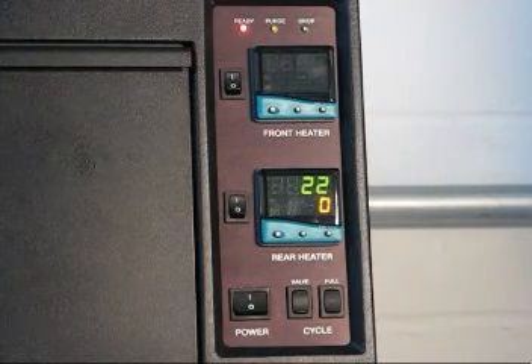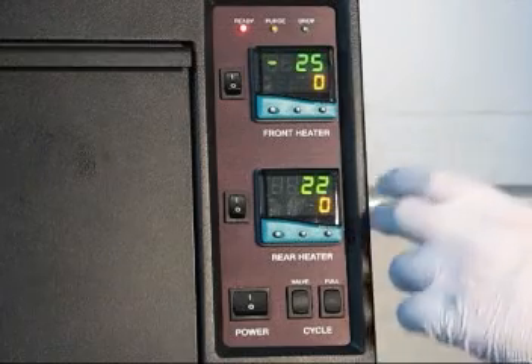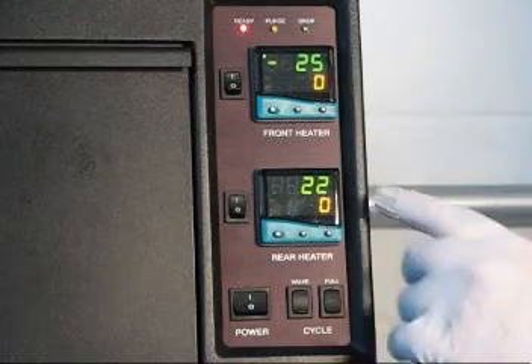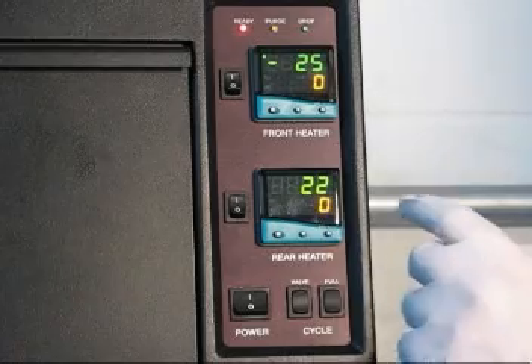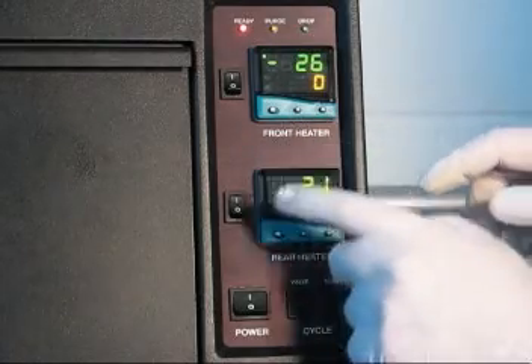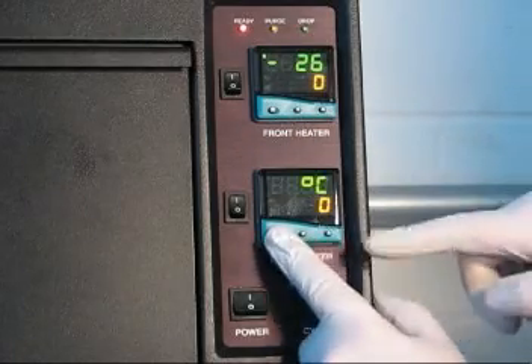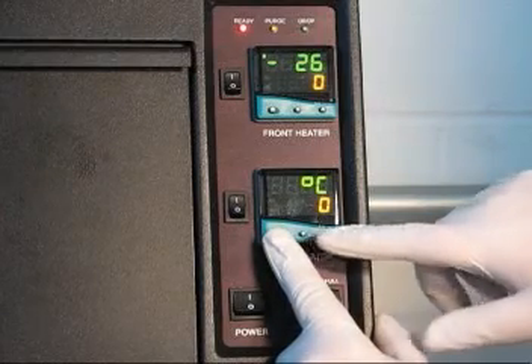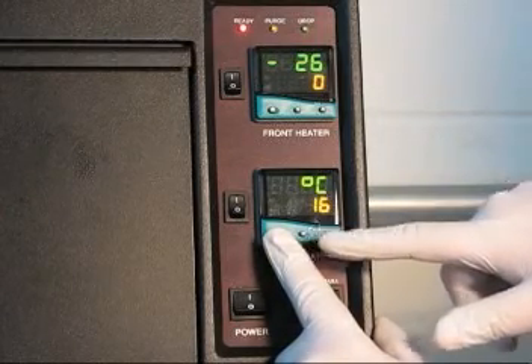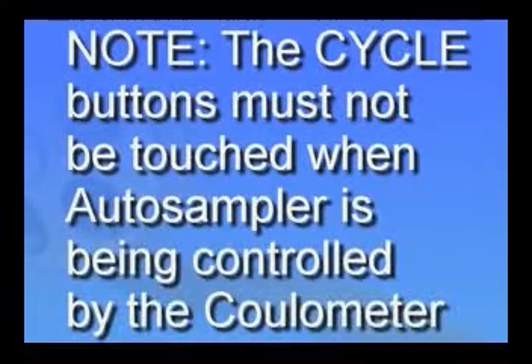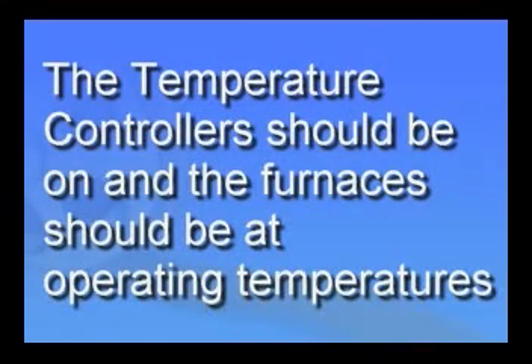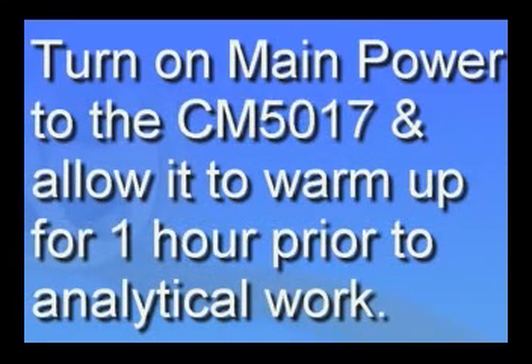Now we will turn on the PID temperature controllers. Each one shows the current temperature with offsets and the set point temperature. To set the temperature, press the star key and hold it down, and use the up and down arrow keys to adjust the temperature. Note that the cycle buttons must not be touched when the auto sampler is being controlled by the coulometer. Temperature controllers. The temperature controllers should be on and the furnaces at operating temperature prior to starting analysis.